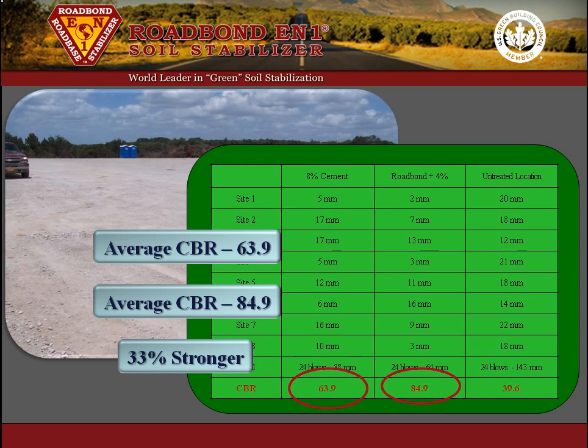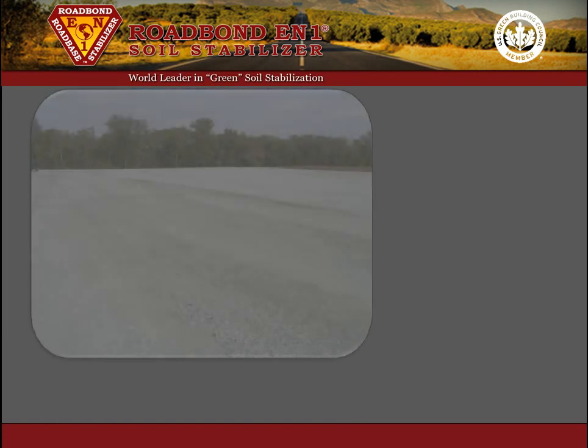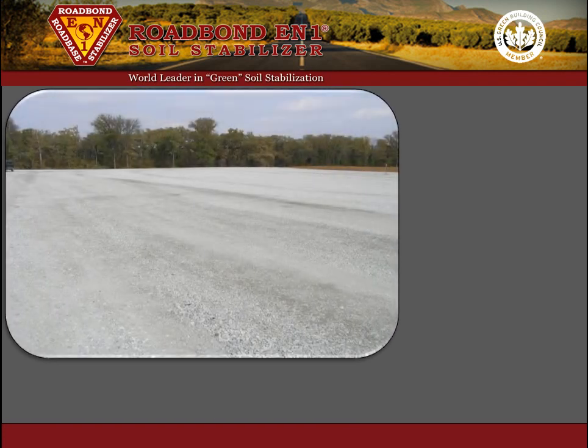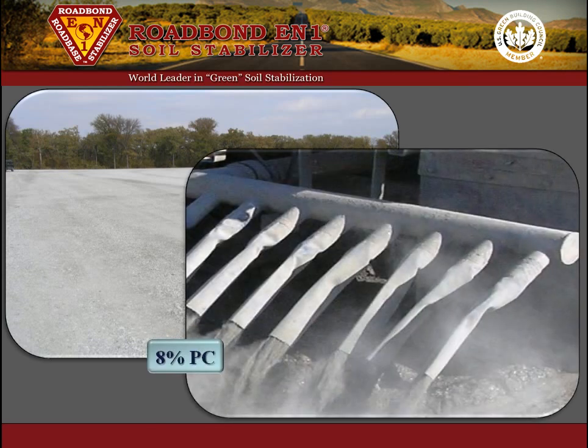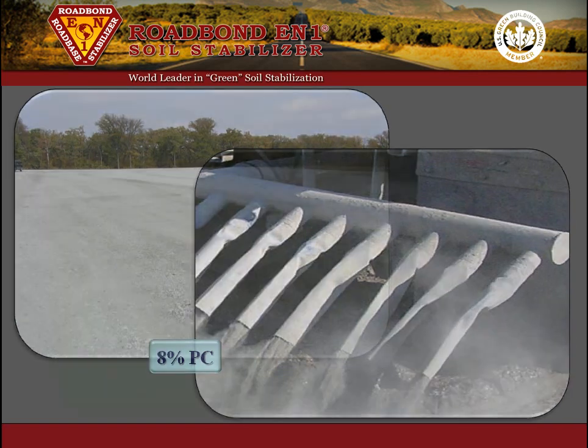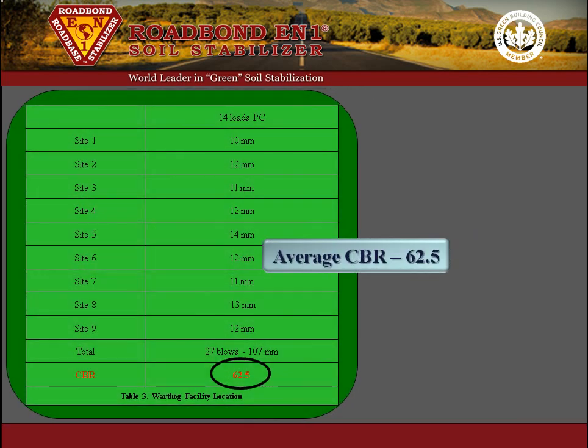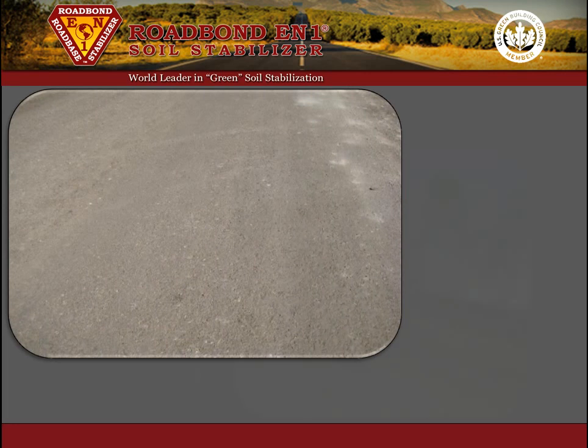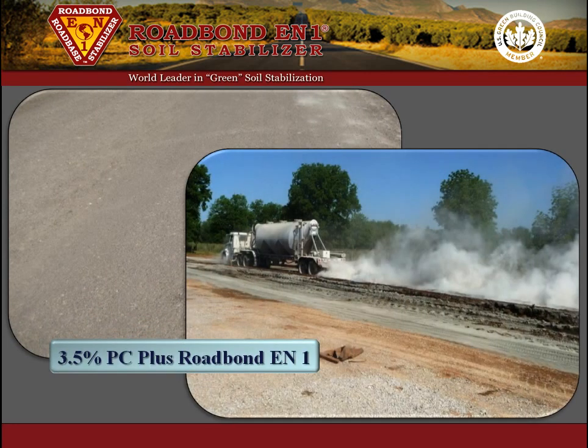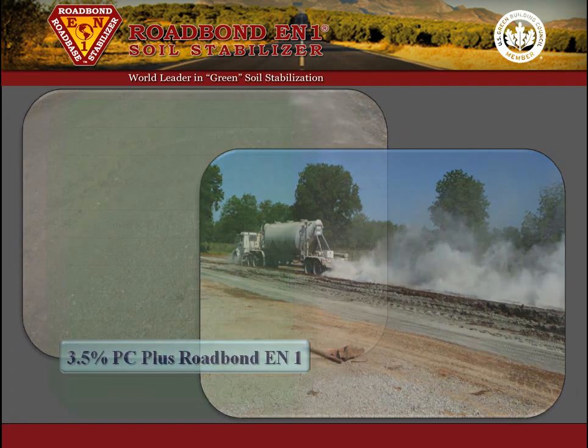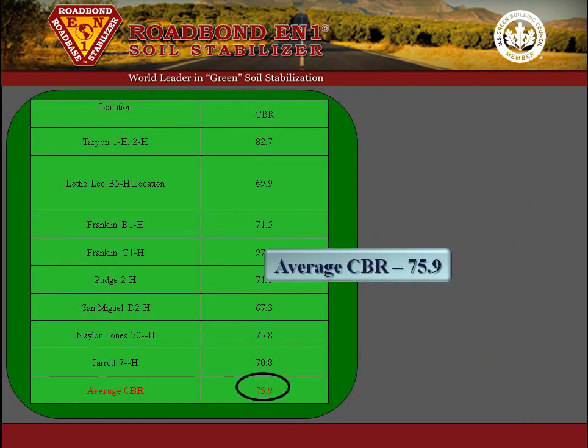Over the next 2 months, 9 more locations were tested. Once more, one of these locations was stabilized with 14 loads of Portland cement and no Roadbond EN1. The CBR of that location was 62.5. The other 8 locations were stabilized with Roadbond EN1 and only 6 loads of Portland cement, which is 57% less Portland cement. The CBR of these locations averaged 75.9 for an increase in strength of 21%.